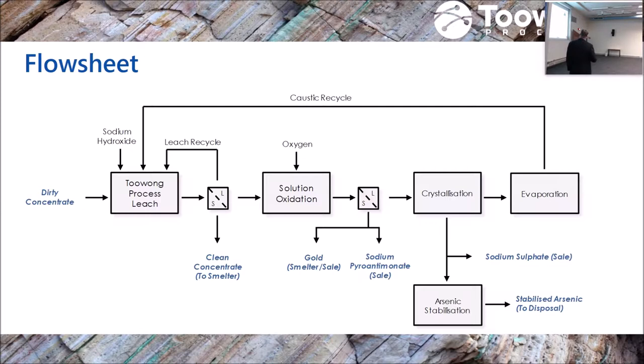This primary leach recycle is actually a very important part of the process, because when you leach arsenic out of the lattice in the mineral here, it basically liberates some sulfide ions. So there are some sulfur atoms that are popping off the surface of the mineral as a sulfide ion, and it's that sulfide ion that helps sort of drive the kinetics, and it's a bit like a flywheel. So this primary sort of liquor, like thickener overflow, coming back in the leach is a very important part of bringing back some sulfides so that we're not adding sodium sulfide in the front end of the process.